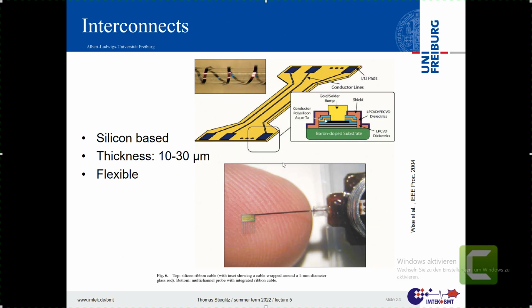Very amazing to me when I read it first is, if you thin silicon down to less than 30 microns, it changes its properties. Normally silicon as a single crystal is very brittle. So if you smash it on the table, it goes into bits and pieces. If it's thinner than 30 microns, it gets flexible. That means you can really bend it, you can even make a knot into such a probe or a cable.